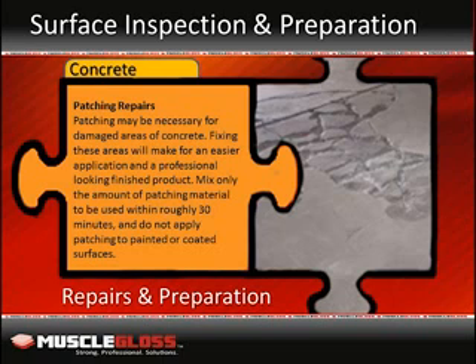Remove loose concrete pieces. Chisel away cracked materials and square off or undercut edges with a chisel and hammer. Use a wire brush to remove crumbling pieces and roughen smooth surfaces. Areas of repair should be free of debris and dust.